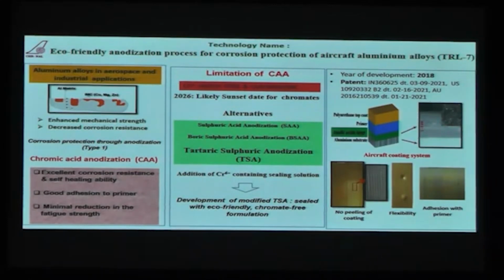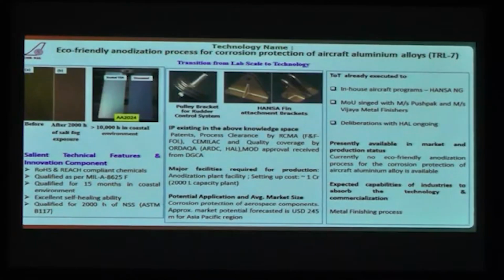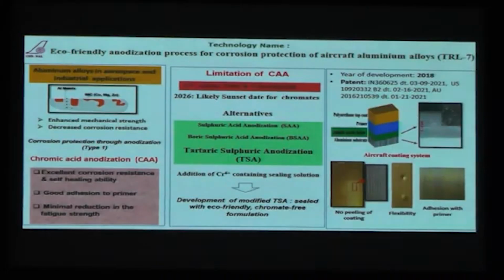Keeping that in mind, we have developed at NAL an alternative process, a modified tartaric sulfuric acid anodization, and we have sealed it with an eco-friendly chromate-free formulation. We have evaluated this alternative coating for a variety of tests. For example, it is qualified as per MIL-A-8625F, which is generally the standard used for the evaluation of even the chromic acid anodization.